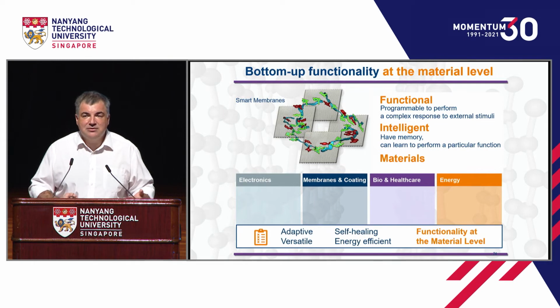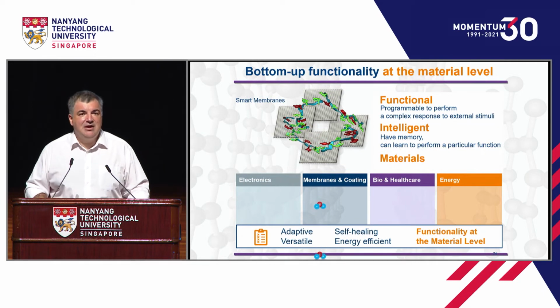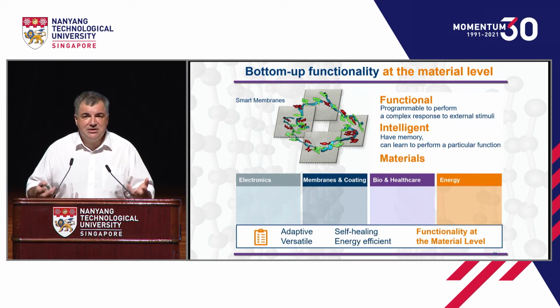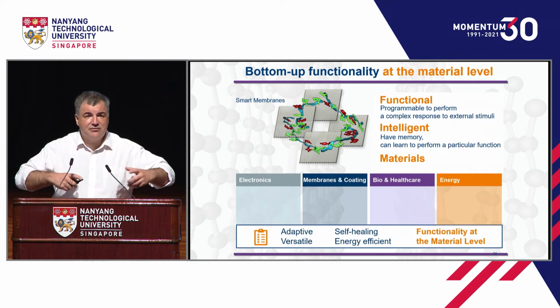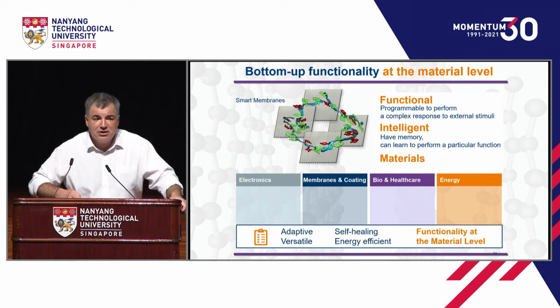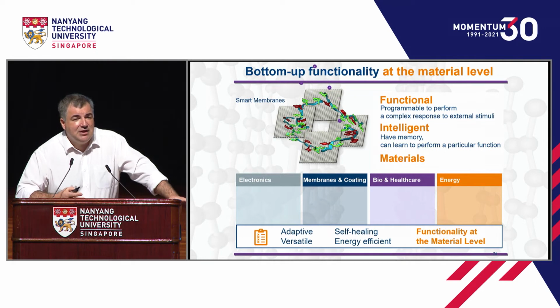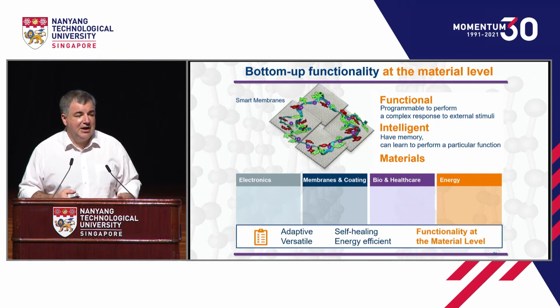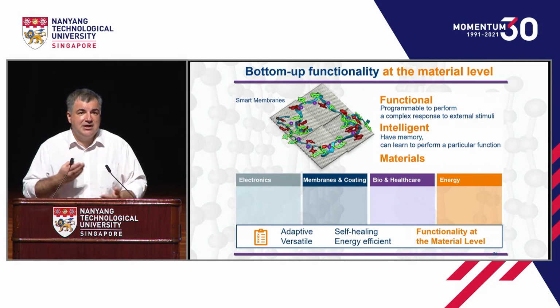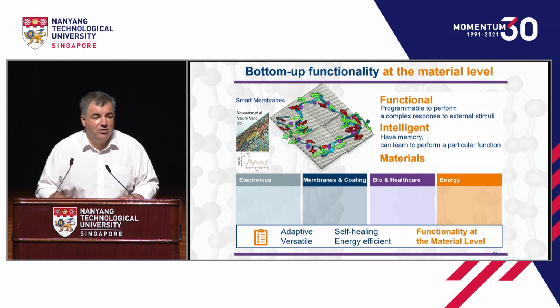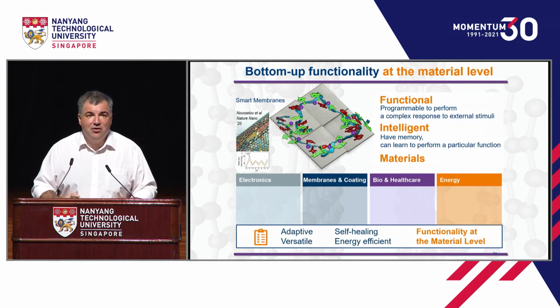One example is that we now produce smart membranes. Graphene is quite good for membranes, for example, for water desalination. But what happens if there are some toxic species in your water stream? What we do is create a heterostructure, and we create those materials in such a way that if there are some toxic molecules, they change conformation, and then they can close those pores and stop the water flow. So that's an example of a functional material.